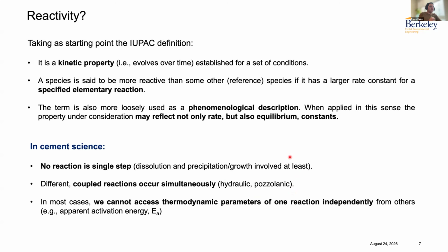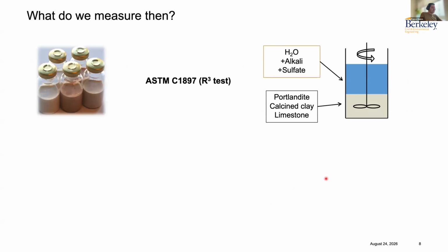And a clear example of this is what we use when we try to apply the so-called maturity method in concrete technology, where we use this parameter, which is an apparent activation energy. Well, it's called apparent because that's not the activation energy of any of the reactions that happen, but in a sense is something that couples that group of reactions happening all at the same time. So for a chemist, this number actually doesn't represent much, but for us it is what we can do considering that we have coupled processes occurring simultaneously.